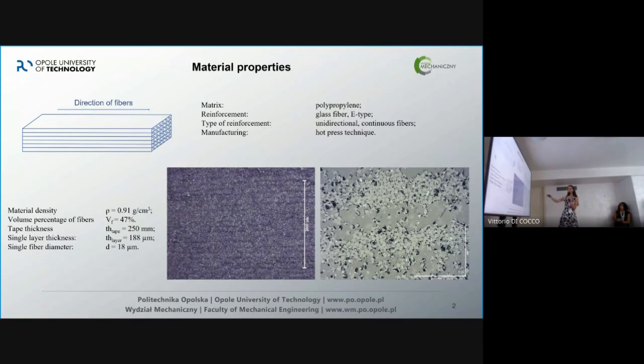So, well, you can see that there are darker and lighter colors, which means that the lighter ones are fibers, and between them there is a matrix. In a perfect material, we would have it totally even, but due to the manufacturing technique, we obtained some parts where we didn't have so many fibers, and there was a lot of matrix, which is not really good for us because this is a weaker part of the material.